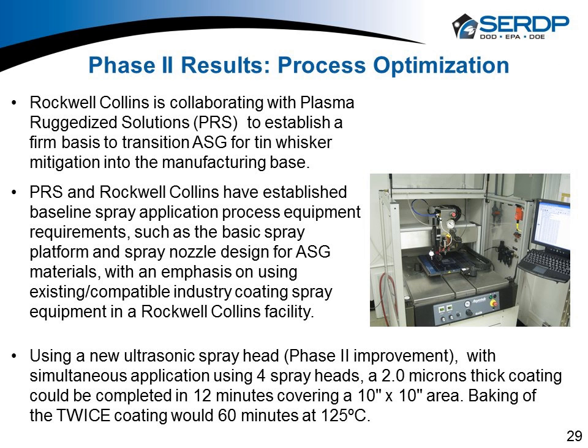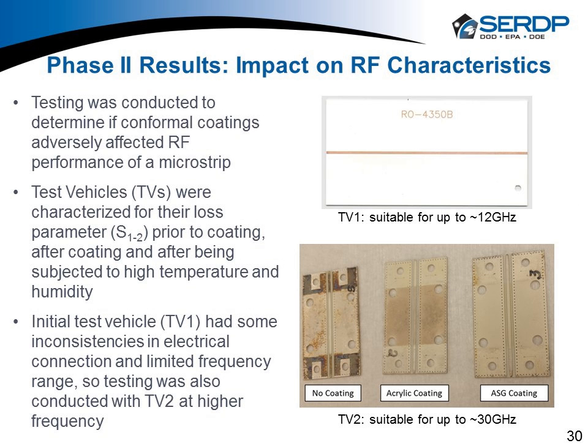And we wanted to try to hit that sweet spot where, when you look at transition to an industrial base, you're more in line with what they're doing. And we were able to achieve that with the new head and doing our machine configuration. And PRS was able to do the same thing, so we were able to replicate that. If I go to slide 30, this is brand new. No one's seen this unless you've read the final report.